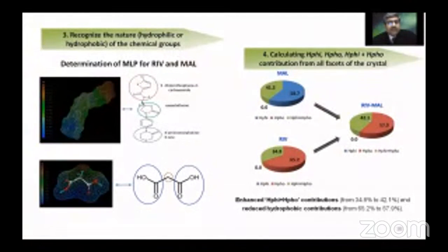This could be one of the reasons for the higher hygroscopicity of the co-crystal as compared to rivaroxaban. So we concluded that the enhanced hydrophilic plus hydrophobic contribution from 34.8 to 42.1 and reduced hydrophobic contribution from 65.2 to 57.9% could be one of the contributors to the enhanced hygroscopicity behavior of the malonic acid co-crystal.